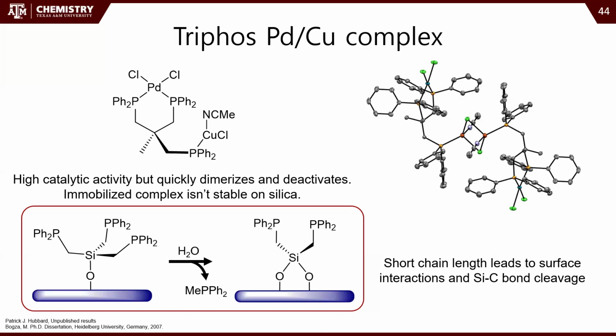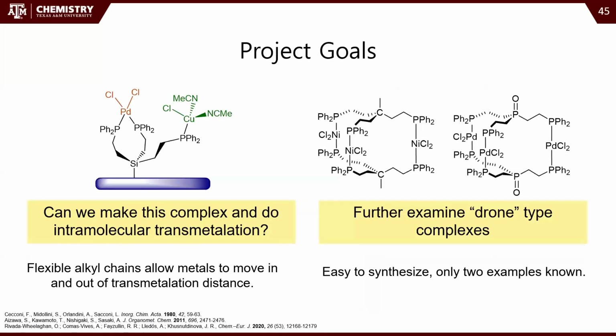So we have to rethink this, and we'll just take what works and add 1 more methylene in there and try to see if that reduces the steric interactions and makes that silicon-carbon bond a little more stable. So we'll make these tripodal phosphine linkers with 2 methylenes. And these ligands show up in the literature a little bit. Interestingly, if you take a square planar metal, like a nickel 2 or palladium 2, it makes these drone type complexes. They kind of stack on top of each other. And so there's only 2 examples in the literature.